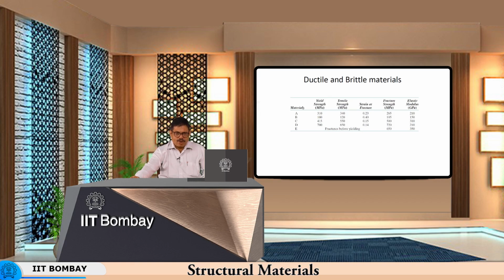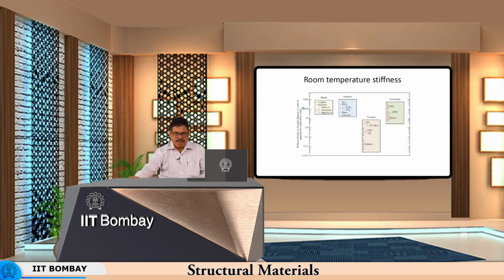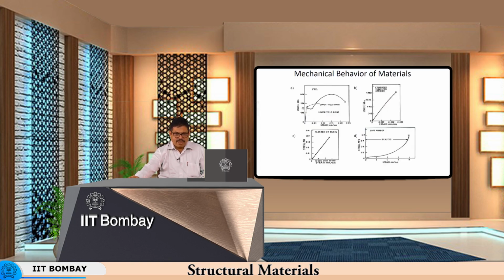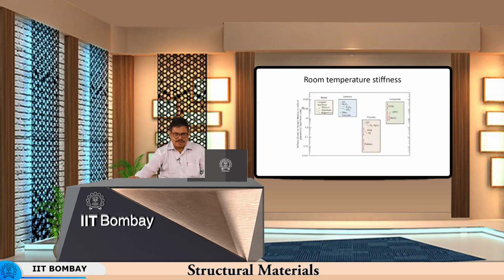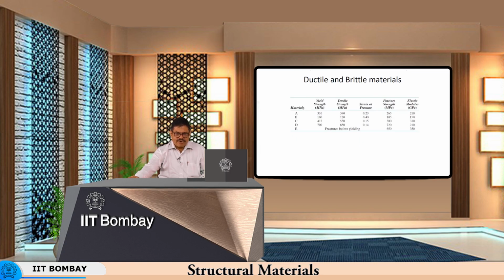Now how do you check whether the two materials are same or different? You see that the Young's modulus of A and Young's modulus of D is the same. So, these two materials are likely to be the same, whereas this material is much more compliant than any others. E fractures before yielding. So, it is something like a ceramic or like plaster of Paris. Tungsten carbide is a ceramic, so it is something like that. It has got fracture strength, there is no yielding, whereas D has got a high strength. So, this is basically like a high alloy steel which has got very small amount of ductility and very high tensile strength.